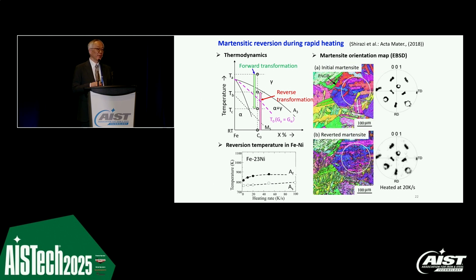So when we have such martensitic reversion, we can get good grain refining by the reversion, because of the so-called austenite memory phenomenon. This is the initial martensite structure, and this is after reversion and quenching. We have the same austenite grain size and almost the same, a little bit refined, martensite structure. Anyway, this austenite memory effect prohibits grain refining during reversion for high alloy steel, so we have to be careful about that.